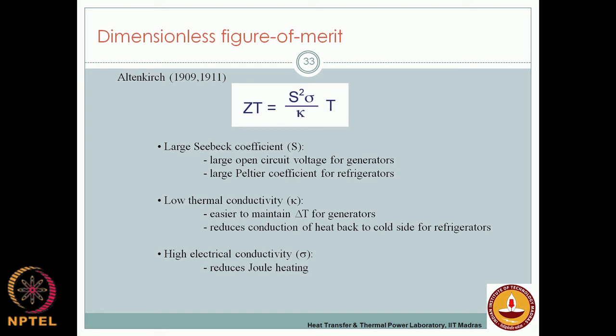Now, if you look at the cases, however, in semiconductors, the Seebeck coefficient, electrical conductivity and thermal conductivity, they are all strongly coupled to each other. So, you cannot say I take a material with a large power factor and a very small thermal conductivity. It turns out that if your power factor is very large, your thermal conductivity also turns out to be large, because for example, if you talk about electrons, the electrical conductivity and thermal conductivity of electrons are directly proportional. Okay. So, higher the electrical conductivity, higher the thermal conductivity. You do not find a material where electrical conductivity is very high and thermal conductivity is very low. Okay. So, therefore, the higher the power factor, the higher the thermal conductivity.